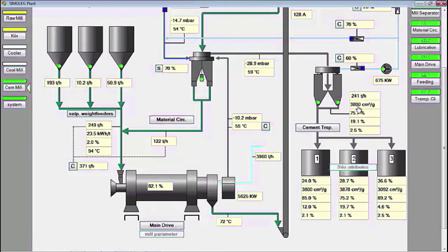then the cement temperature is still low at 72 degrees Celsius. Under normal operating conditions the cement temperature is between 85 to 95 degrees Celsius. In controlling the operation of this cement mill, it is expected to be optimal, which means that product quality stability can be obtained, then all operating parameters are in a stable condition and do not fluctuate.